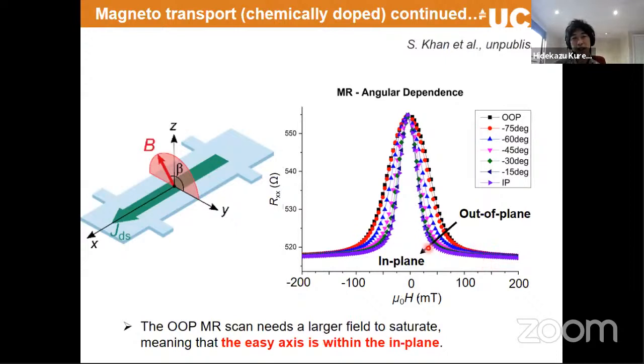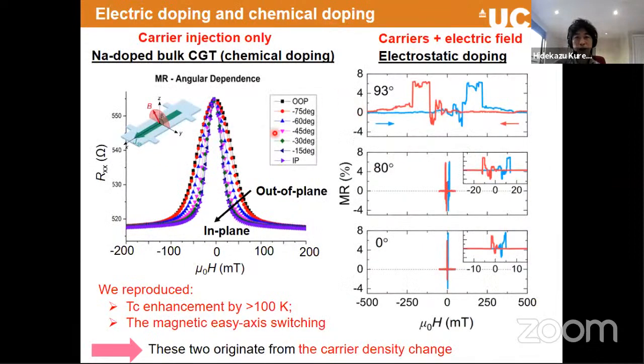This clearly suggests that the magnetic anisotropy is in the in-plane direction, because this requires less magnetic field to fully saturate. So that's actually consistent with the electric doping experiment as well, because we switched the anisotropy from out of plane to in plane by the doping. All right, so now we can compare between these two, that was the initial motivation. What we can tell by comparing these two is that carrier doping, in both cases, can increase the Curie temperature and also promote the switching of the easy axis from out of plane to in plane. What's different is the shape of this magnetoresistance curve.